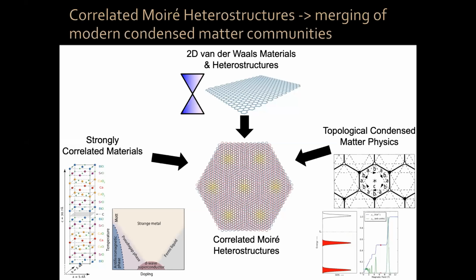Your second question, remind me, was about... Is there any specific Moiré exciton features at the charge neutrality point in twisted graphene? So some people think that, at charge neutrality, depending on conditions, there may be a gap or not, and there could be interesting excitonic physics at the charge neutrality point. I don't think anyone has evidence of it. People have looked at interesting interband transitions, because even though I didn't show you, the remote bands are much more dispersive near the gamma point, but they also flatten near the K points. So you have interesting optical transitions, flat band to flat band near the K points.